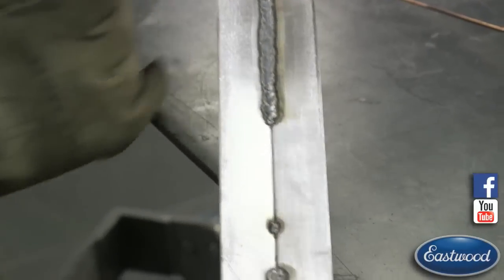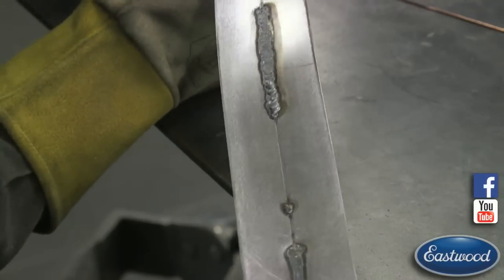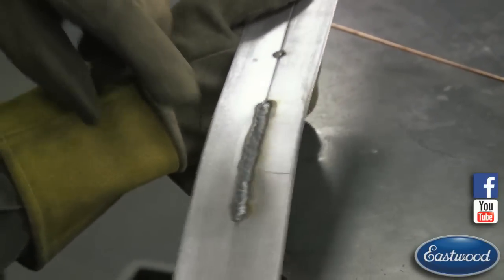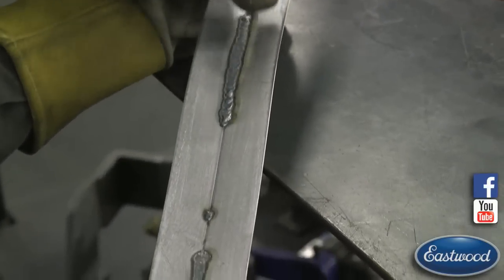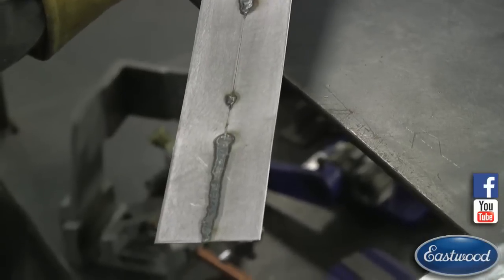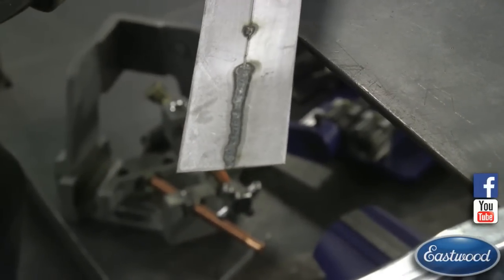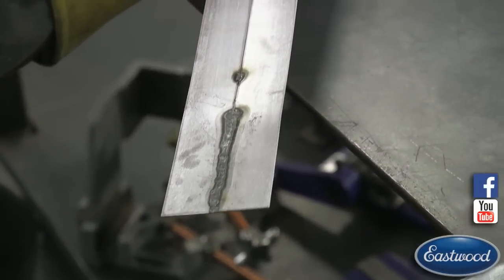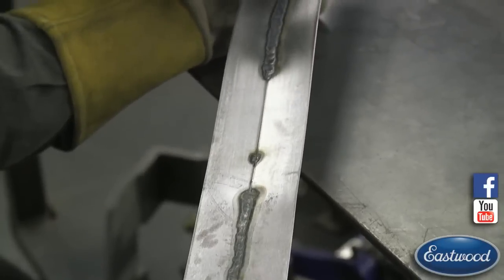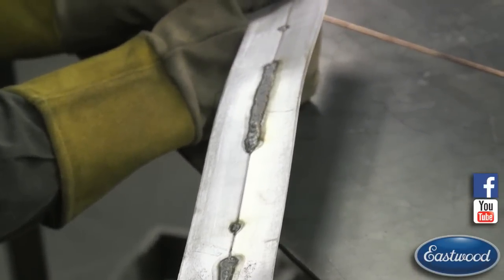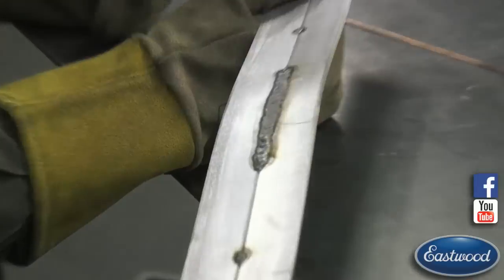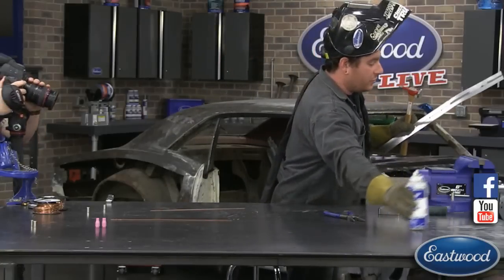And the warpage is quite a bit bigger. You can see just the weld puddle in general is probably twice the size of what we had down here. So because of that, the heat area is probably twice the size because the puddle's twice as big. We're heating up a bigger area, we're warping more metal. That's going to cause that problem. So, good. Let me hammer on it, just keep this from turning into a pretzel by the end here.